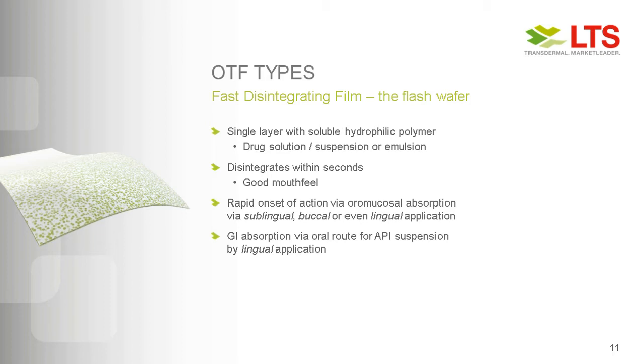The first type, the fast disintegrating film, or as we call them, the flash wafer, are mostly a single-layer OTF with very highly soluble hydrophilic polymers as a film former. And the drug can either be dissolved as a solution in this film or be suspended or as an emulsion. These films shall disintegrate within seconds. So best case, 5 seconds roughly, sometimes a bit longer depending on the thickness and the loading with API.